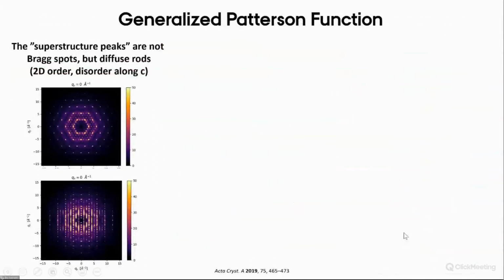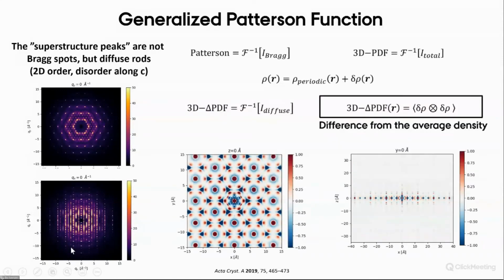But in reality, these are not Bragg spots. I had a new student at this point, Nikolai Roth, and he took the crystals to SPring-8, and yes, you could see extra spots in the layer, but when you look perpendicular, these spots are really just a cut through these very, very diffuse rods. So there's clearly disorder in copper selenide. And this is where we then have to generalize our crystallography a bit.